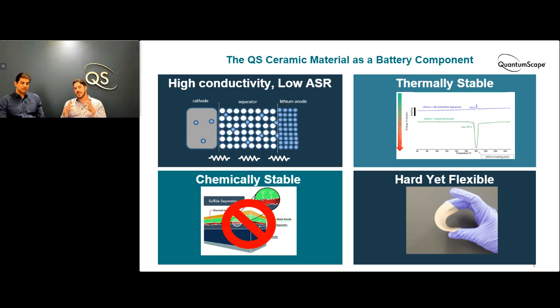Of course, they're also chemically stable. So again, having a material in contact with lithium metal for a long period of time is a very aggressive environment. Lithium is a very reactive chemical, very reactive metal, and it will attack and react with many, many different ceramic materials. Our particular ceramic, we've seen, is very stable against lithium metal over a very long time, and also against the cathode components as well.